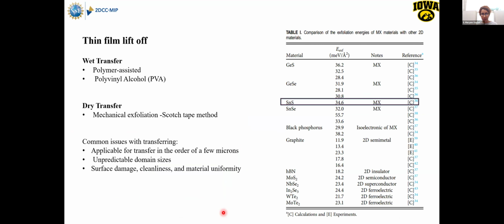The problem with transferring this thin film, if you look at this data right here, is that these have a very low exfoliation energy, and these are the materials people have played with so far. However, even with these materials, they can only transfer on the order of a few microns, and this has an unpredictable domain size and usually surface damage, even with this low exfoliation energy.